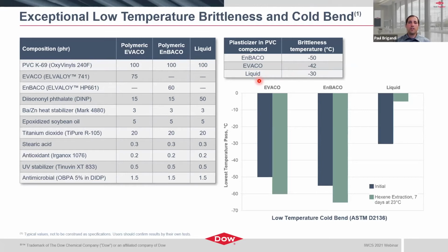And this is important for those applications where we start talking about cable ratings and installation environments that require, you know, down to minus 40 C performance, right? So incorporation of these polymeric materials at the low temperatures imparts that flexibility. It's largely driven by, I'd say, the Tg of the polymer, but in these particular cases, then the extent of branches and length of those branches or side chains within the monomer, whether butyl acrylate or vinyl acetate.